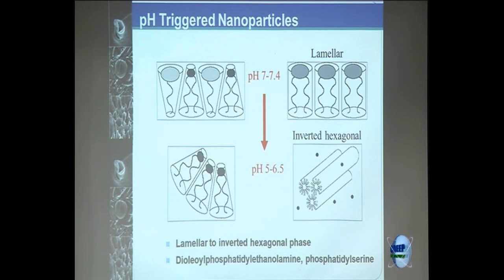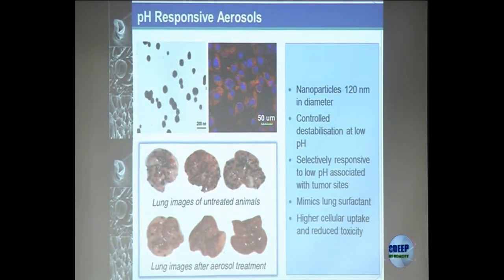There's also the concept of trying to have pH triggered aerosols. In this case, you can package these particles so that they are in a lamellar phase and are stable at pH 7 to 7.4, which is the normal pH in the body. And in the disease site, as the acidic pH environment comes in, these then change to an inverted hexagonal phase and cause a preferential release of drug. To show you an example of this, these are 120 nanometer particles of ethanolamine phosphatidyl based particles, and these were delivered as aerosols which have then micro droplets of 1 to 3 micron aerodynamic diameter and can go into the deepest parts of the lungs.